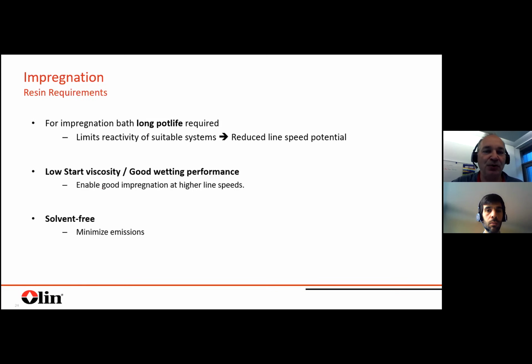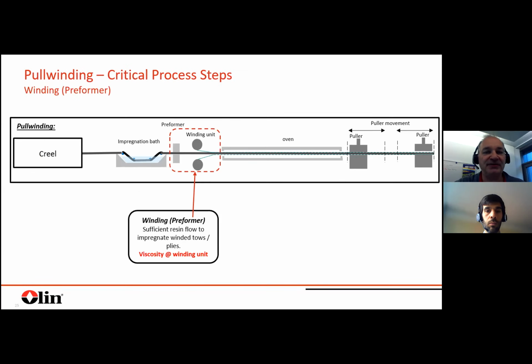As mentioned, key requirements from an impregnation point of view on the resin are a long pot life, which is a limitation for our reactivity, low start viscosity, and good wetting performance. So lower viscosity helps for sure. And it should be solvent free, just from an EH&S point of view, to minimize the emissions, as you often operate in an open bath. So the next critical step would really then be the winding unit and preforming.